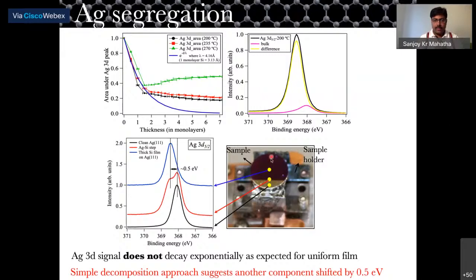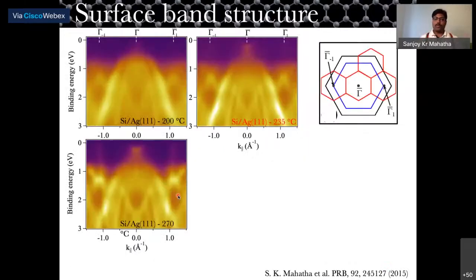Okay, so on this blue curve is totally shifted from this black curve. And this silver is basically silver on top of silicon. So what is happening when we are growing them, the silver is going on top of the silicon. And then we did this angle-resolved photoemission spectroscopy of these structures grown at different temperature, and we can see that these structures' valence band structure is like this.